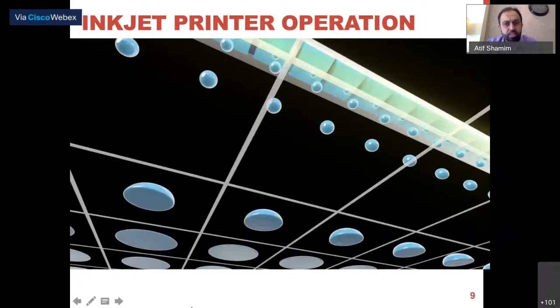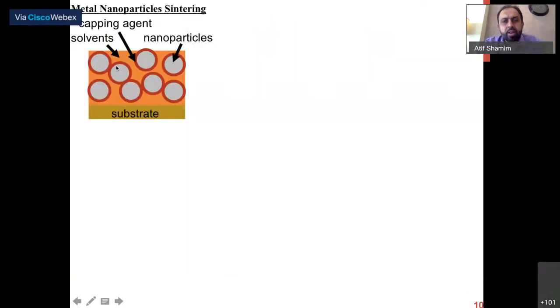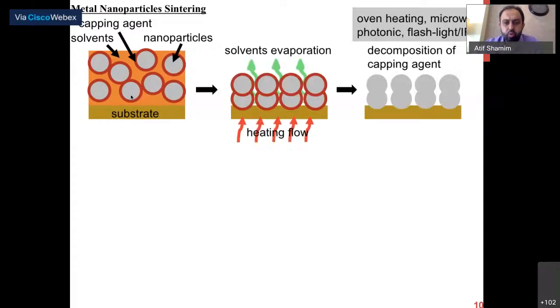So what we do is that we start heating. The traditional way is heating, but there are a number of ways you can do it. And this process is called sintering. You could use lasers, photonic sintering, other methods, a conventional oven. Eventually you evaporate the solvent and you melt the capping agent. So now these metal nanoparticles are free to form continuous traces. So you keep on sintering them and then you could see conductive patterns. We have seen from experience that the higher the temperature you apply for sintering, the better conductivity you could get and the better